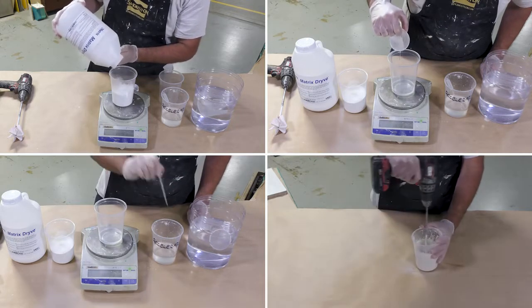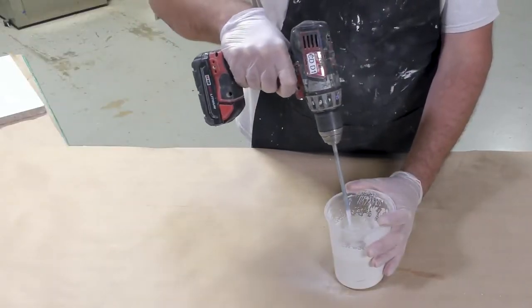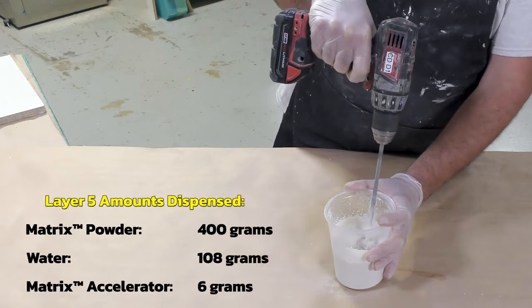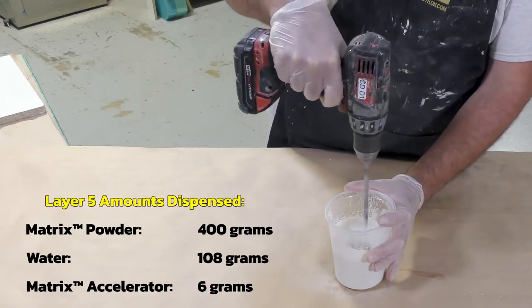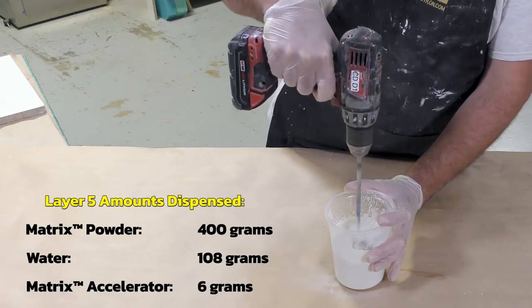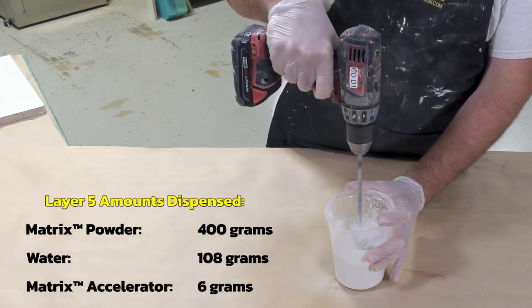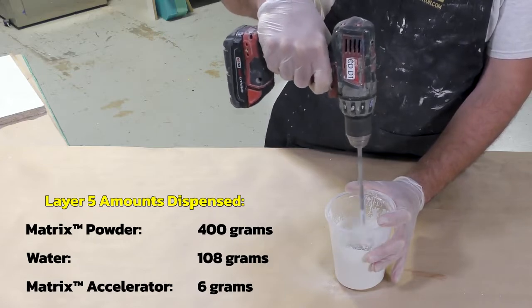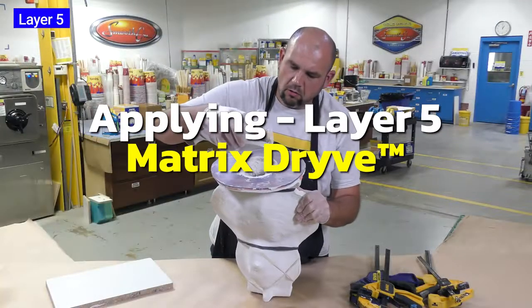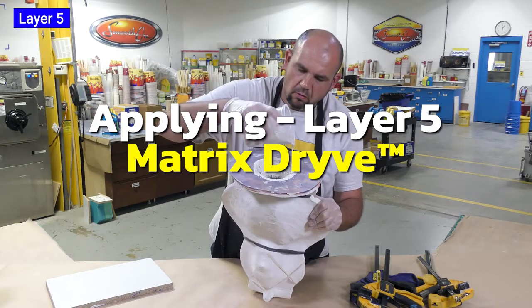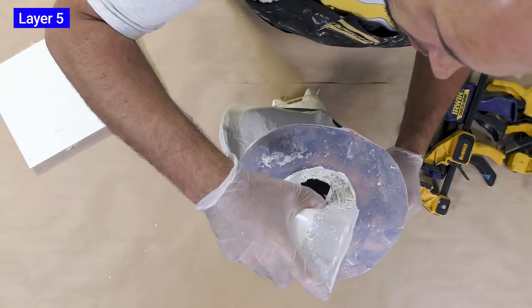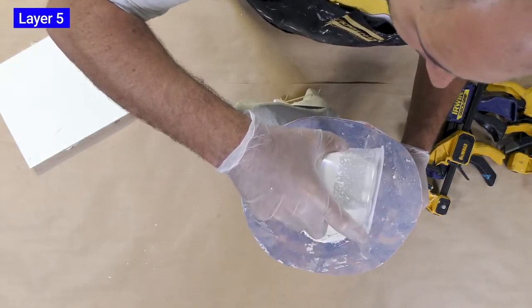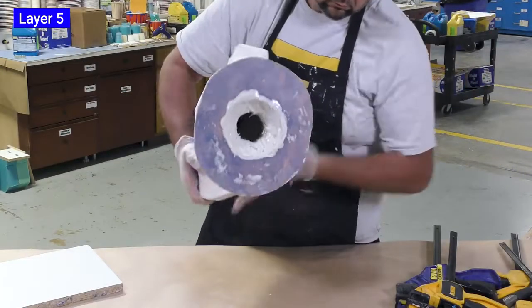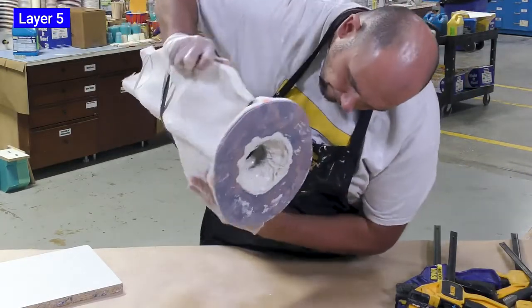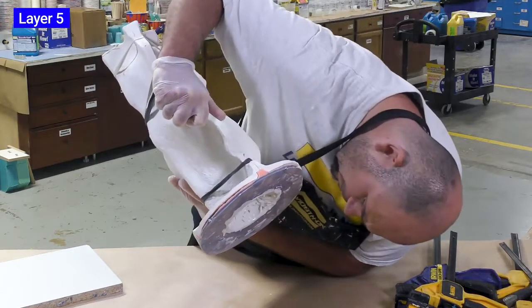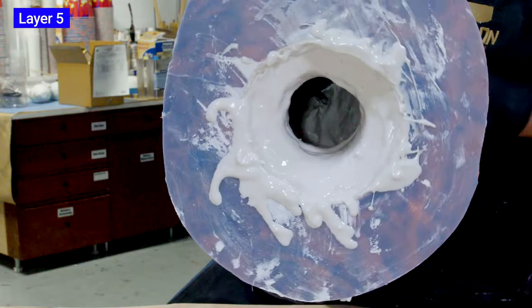Just like the first and second layer, we're going to dispense the same quantity of material for this fifth and final layer. We're dispensing 400 grams of the matrix powder, 108 grams of water, and 6 grams of the matrix accelerator. The three components are mixed thoroughly before being poured into the mold. And once it's mixed, we're going to pour it inside the mold and we're going to rotationally cast the material again, making sure that the glass fibers inside are fully encapsulated in the Dryve material. We want to make sure that the entire inside of the mold is covered with a fresh layer of material.